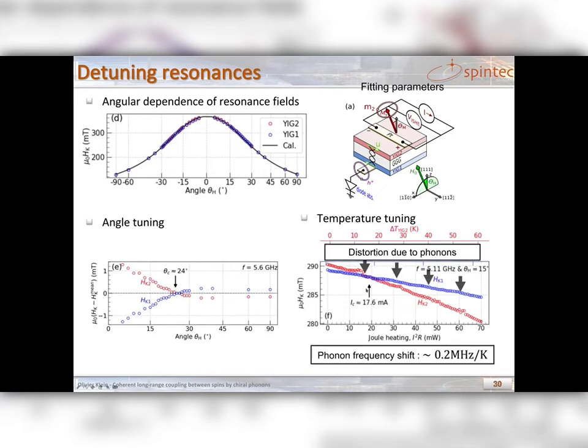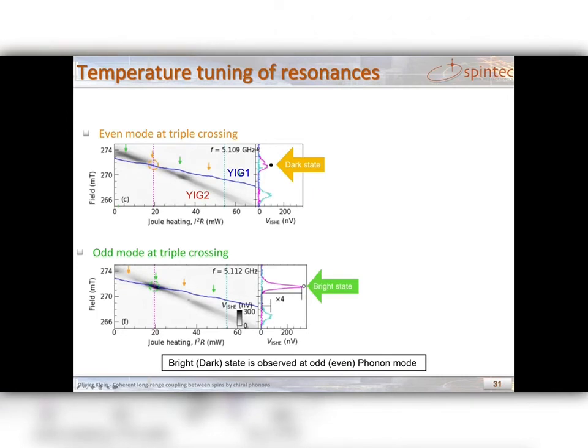If you look closely, there are some small distortions in the blue line, which are due to magnon-phonon coupling. Although we use a single frequency, we see multiple phonon lines here, because phonon frequency changes with heating, and this is due to the fact that heat changes the lattice density. So we know from the temperature increase and the sound velocity that the change of phonon frequency is about 0.2 MHz per Kelvin.